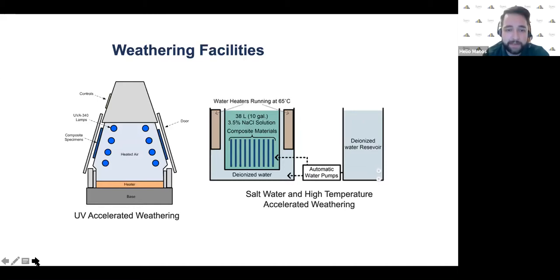we place the specimen in a saline solution. Typically, we have it at 3.5% sodium chloride, which is about the average salinity of the oceans around the world. And we have heaters that heat distilled water to keep the saline water at a constant temperature. So the temperature that we set this to depends on the material. Typically we will stay below glass transition, so we are not changing the mechanical properties by introducing very high temperature. At the same time, we want to be as high of a temperature as we can below this transition zone so we can get higher acceleration rates.